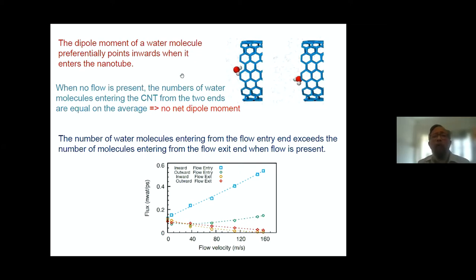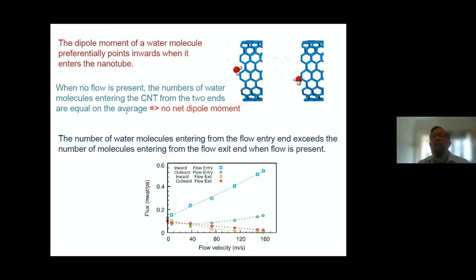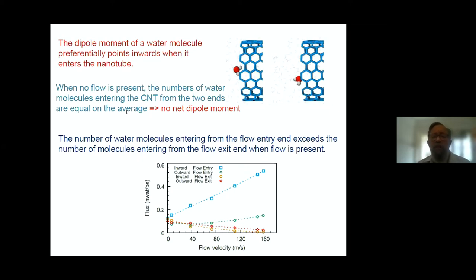When there is no flow, the two ends of the nanotube are equivalent. On the left-hand side, water molecules go in with the dipole moment pointing to the right, and on the right end, water molecules come in with the dipole moments pointing to the left. These two cancel each other and there is no net dipole moment. But when there is flow, the number of water molecules entering from the left is much larger than those entering from the right. As a result, this symmetry is broken, and that is why a net dipole moment is generated.